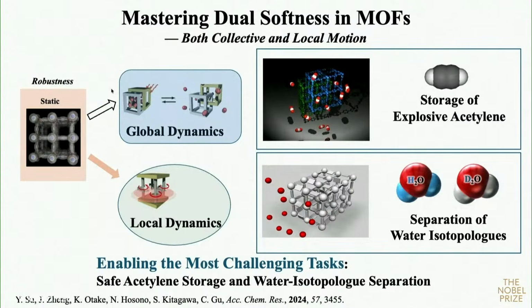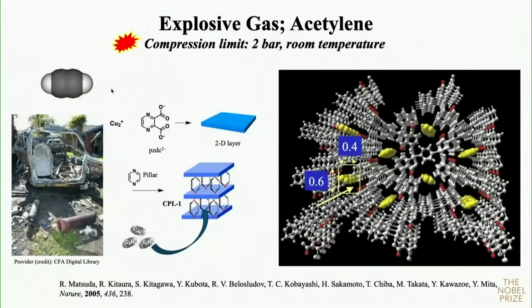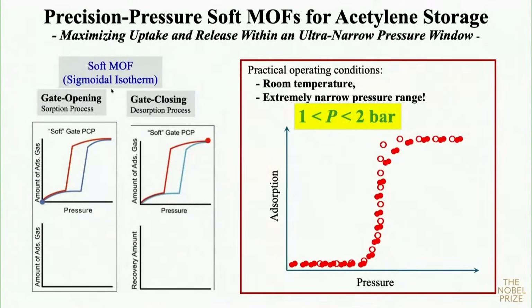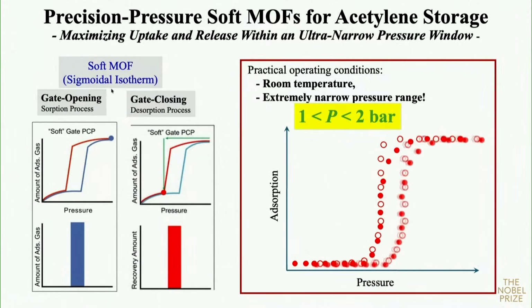There are two types of flexibility. The first is global dynamics. The second is local dynamics. For the first, consider acetylene gas. Acetylene gas is dangerous. If we compress it to 2 bar at room temperature, an abrupt explosion occurs. But we were brave enough to accommodate acetylene in our MOF compound, and finally we succeeded in getting this type of acetylene sorption and storage material. But for a usable material, we need to control the gate pressure. The sorption is like this, but we have to use acetylene again. So we need to control the gate closing pressure. What is difficult is that the pressure range is very narrow, larger than 1 and lower than 2 bar. How can we control this?